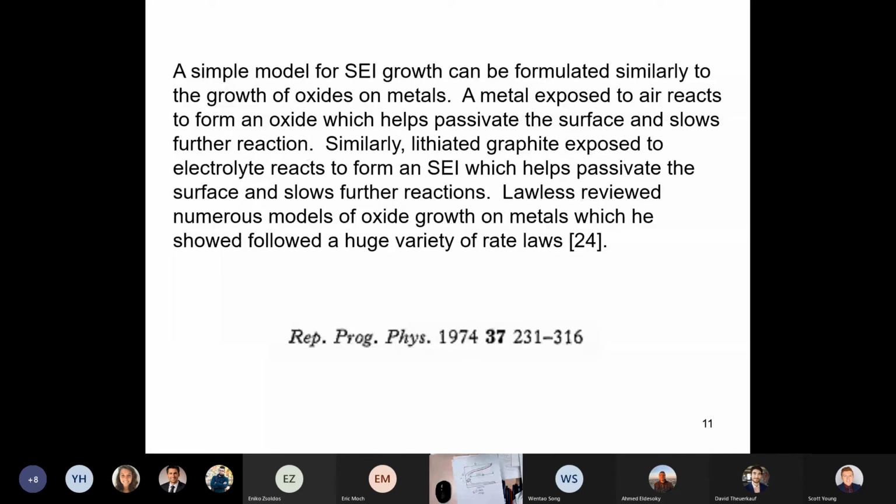And actually, for many types of cells, once the cathode electrolyte interface is pretty stable, all the capacity loss in the cells is due to the negative electrode lithium inventory loss on the growing SEI. Certain classes of electrode materials that lead to high energy density cells have issues at the positive electrode, but more modest positive electrode materials like LFP don't really have a lot of issues on the positive side. So I'm going to just focus on the negative side.